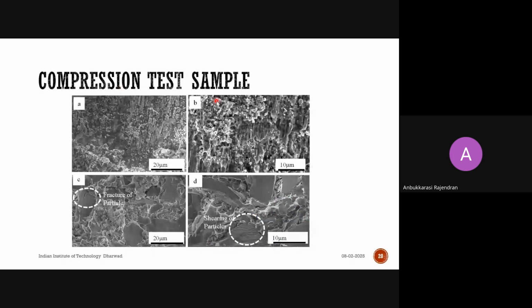Again the same sample, as it is a ceramic reinforced metal matrix composite, we cannot carry out the tensile test, so we did a compression test. Here I am covering two things. One, a testing method: if it is a composite material, we like to go for the compression test instead of the tensile test. Second, even tested samples you can analyze for understanding the fracture behavior. Some of the matrix region, how it fractured, and the particles also got fractured during the test.